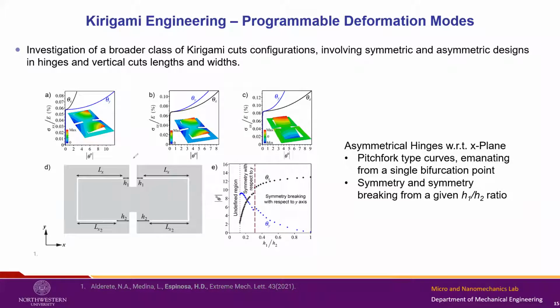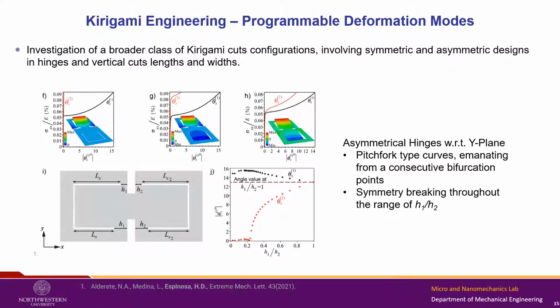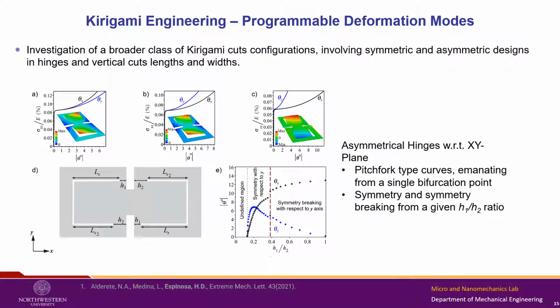So, for instance, in this design, this is symmetric with respect to the x-plane. Then, if we have symmetry with respect to another plane, what we observe is that we no longer have bifurcation emanating from a single point, but now we have sequential bifurcation. So as you stretch, one of the plates bifurcates and starts, let's say, moving upwards, or deforming out of plane. And then as you continue, another plate starts exhibiting that bifurcation, and so on. And we studied other more complex scenarios where we play with these symmetries. In this case, this is what we call an XY symmetry. And again, we recover some interesting properties from bifurcation.